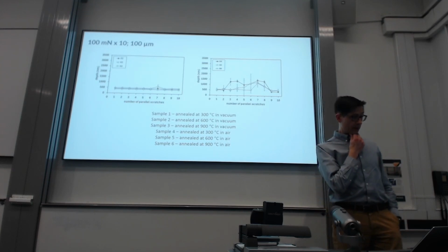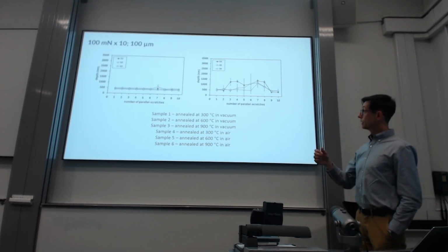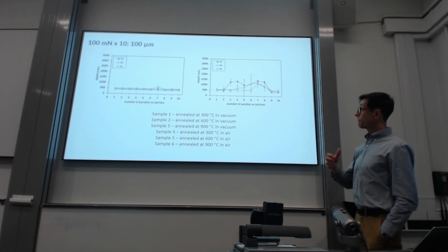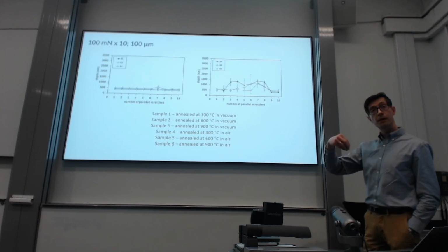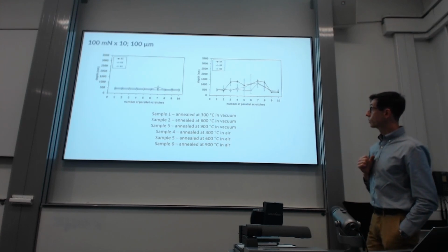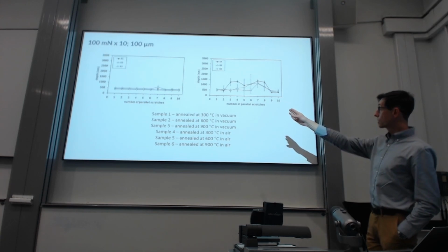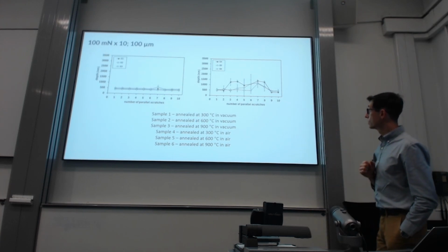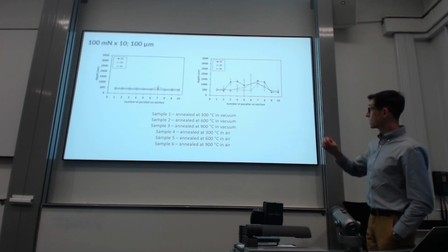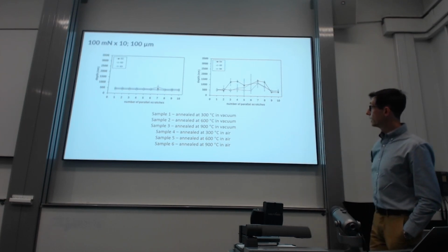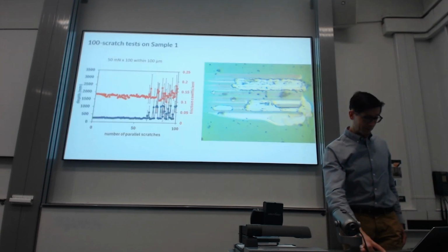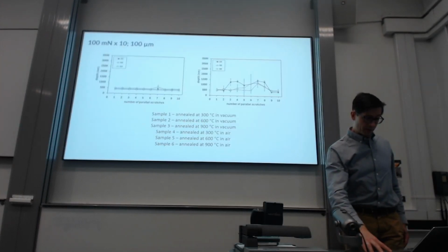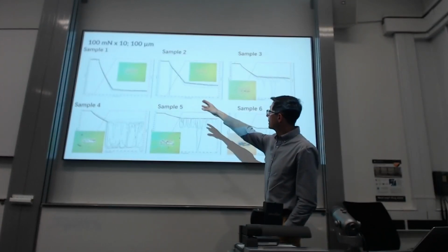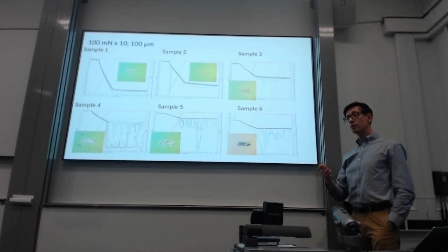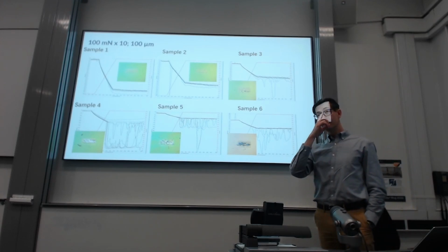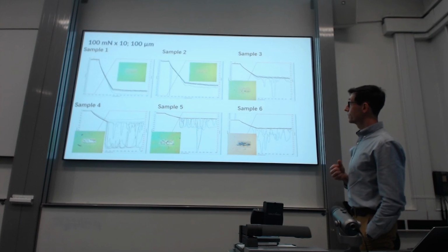So what you can do with this type of experiment, you can also collect your data in terms of depth as a function of number of parallel scratches. In that case we had 10 scratches. Samples 1 to 3 are grouped together, and samples 4 to 6 there. Again, very clear difference between vacuum annealed samples and air annealed samples. Sample number 1, if you look at that graph and image there, performed best in this type of experiment. So we decided to put it to a bit more stress in this type of test.